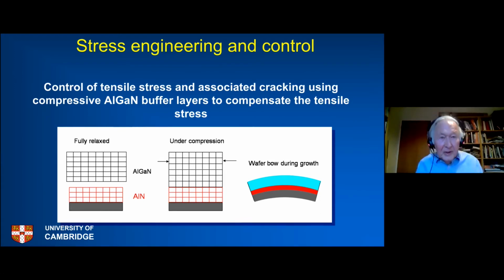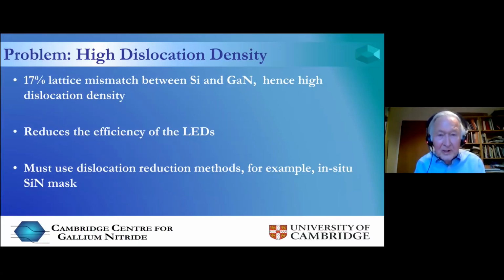And then the third problem is to try and overcome this high dislocation density, because it reduces the efficiency of the LEDs. And so this is a very clever method, which if anyone talked to you about it, you wouldn't believe it, but it really works. What you do is you introduce a silicon nitride mask. So this is a schematic of what is done.